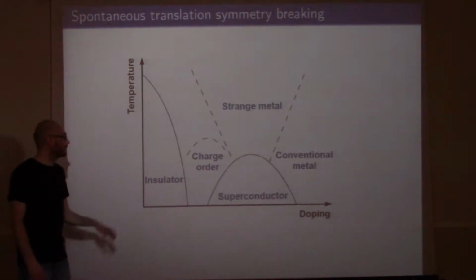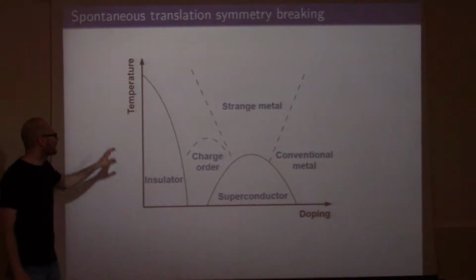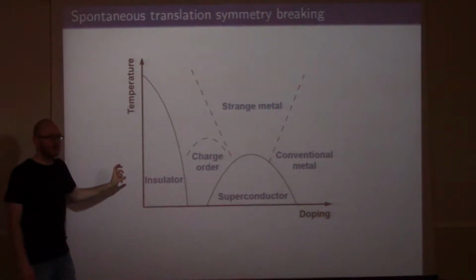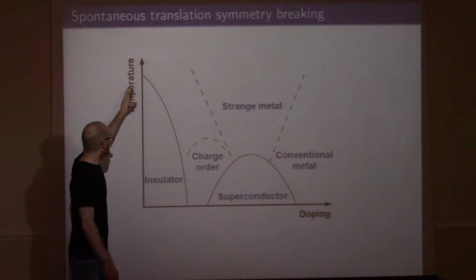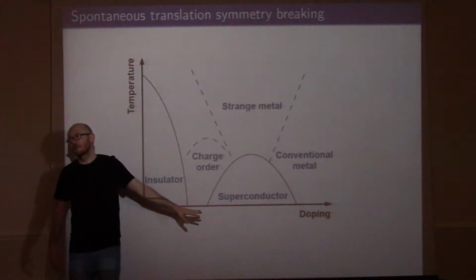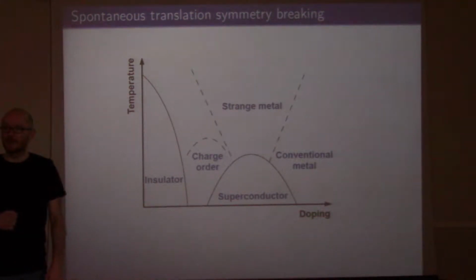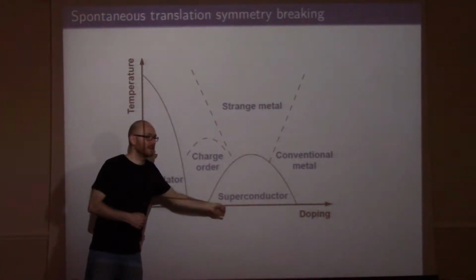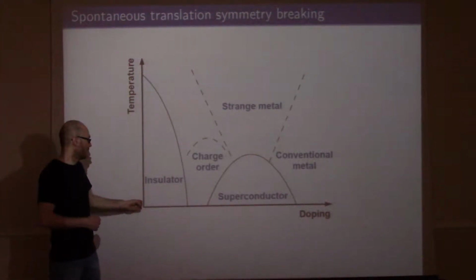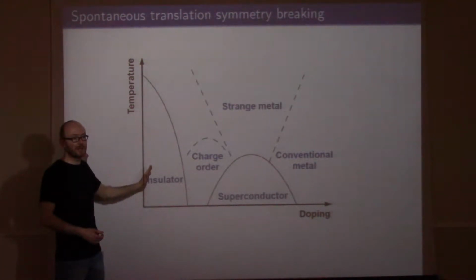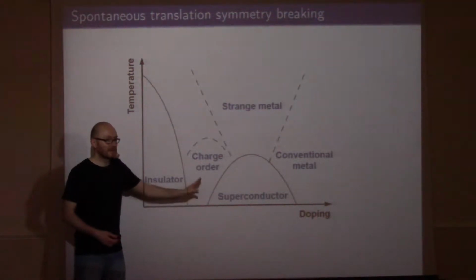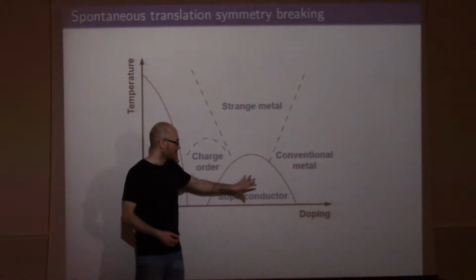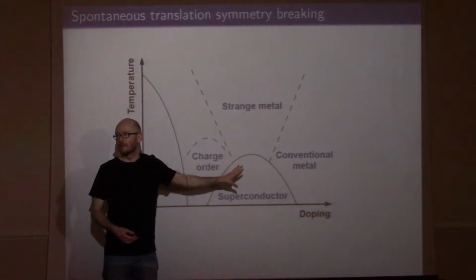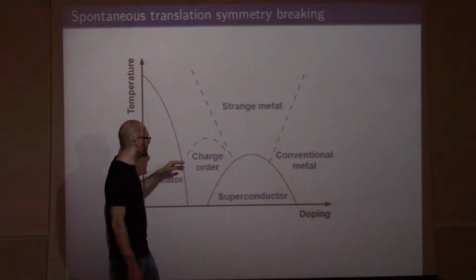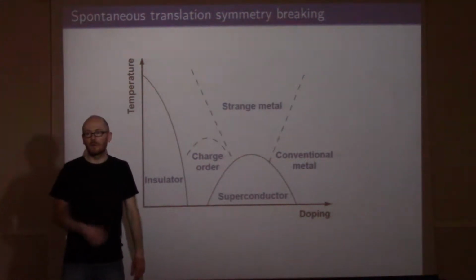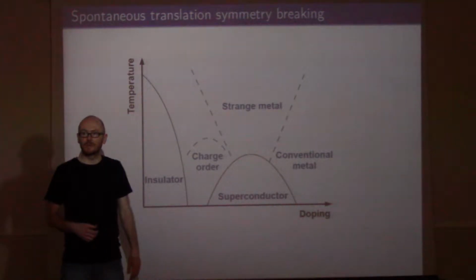Okay, so why do I want to start talking about spontaneous symmetry breaking? So this is a schematic depiction of the phase diagram of high-Tc superconductors. This is temperature on the vertical axis and doping on the horizontal axis. Doping is just telling you something about the atomic composition of the material. Essentially, it's a measure of how many charge carriers are available. So at zero doping, there are no conduction electrons, so you have some antiferromagnetic insulator, nothing moving. Then you start doping it, and the material starts to conduct. But there's this superconducting instability that you hit very quickly for mid-doping values. And it's called high-Tc superconductivity because the maximum critical temperature is usually way above what can be explained by the BCS theory of superconductivity.